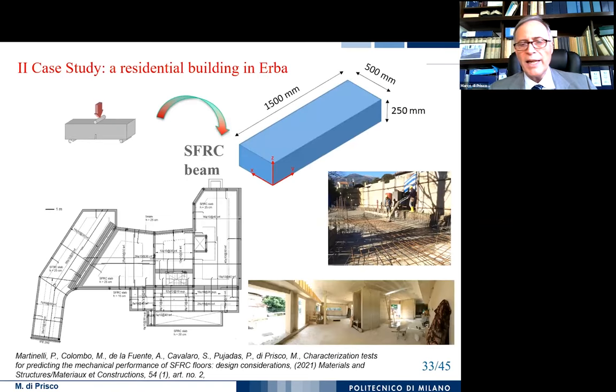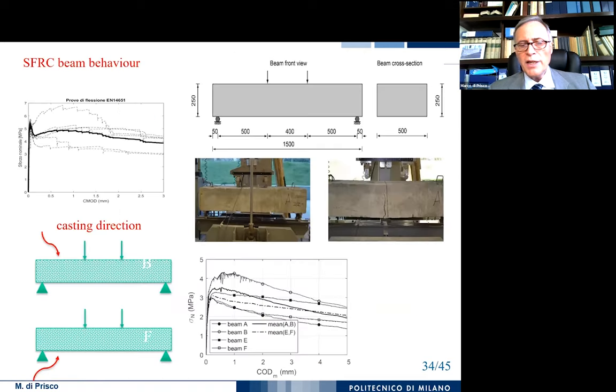Now, looking at a real beam, we used for a floor in a residential building. We tested according to the EN14651. We cast, changing the casting direction, beams characterized by 1.5 meter of length and 250 millimeter in depth and 500 millimeter in width. And we obtain the final response given in this nominal strength versus crack opening graph.